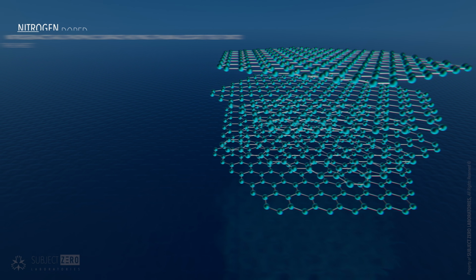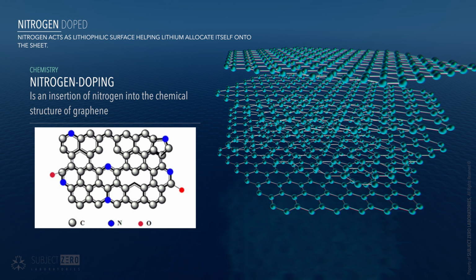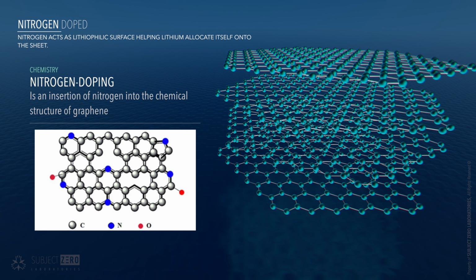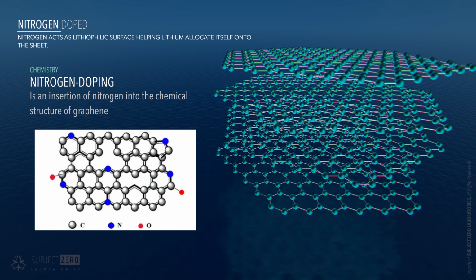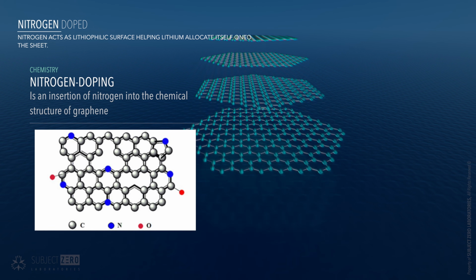The reason they used nitrogen doping was to improve electrode-electrolyte interactions by creating lithophilic surface moieties, which is nothing but distinct sites on the sheet that facilitate nucleation, or simplifying to the extreme here, a place for lithium to allocate itself to. This has several advantages for high energy density and fast charging capability, and as we will see next, this is one of the reasons they were able to achieve phenomenal results.